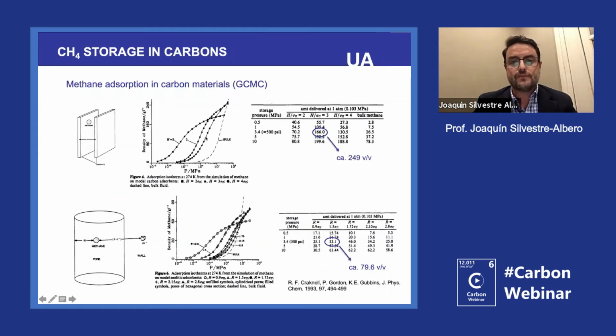We were taking a look at the literature, and there was this nice paper from Professor Gubbins, where he was doing theoretical predictions, and he was doing Grand Canonical Monte Carlo simulations of two different types of pores. On one side, they were just evaluating slit-shaped pores, so something similar to what you have in carbon. And they were also just modeling cylindrical pores to mimic what you can have in a zeolite. And then they were checking the density of methane in different pore cavities.